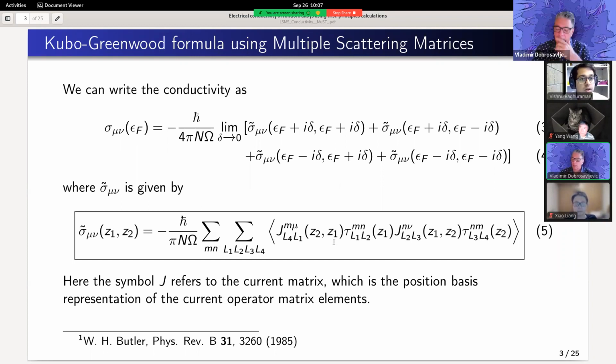So yeah, the reason I'm asking, I've seen some calculations where people do, for example, DFT with molecular dynamics at finite temperature, and then the atoms start to move around. Right? And then for each configuration, you can do a DFT calculation, and there will be displacements of these atoms due to thermal fluctuations, treated as static. That will give you an additional form of scattering, and you can think of this as phonons, right? Which can be done similarly here. It's just the question of how you compute your scattering matrices, right?